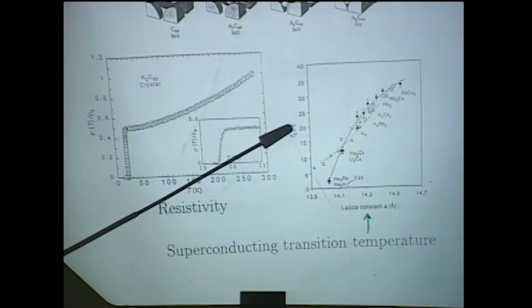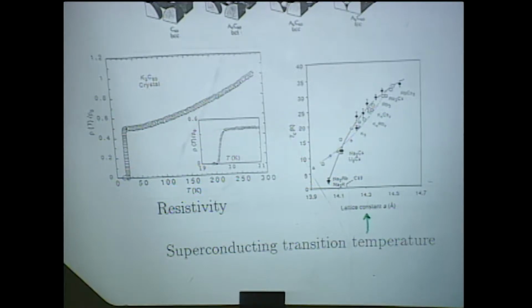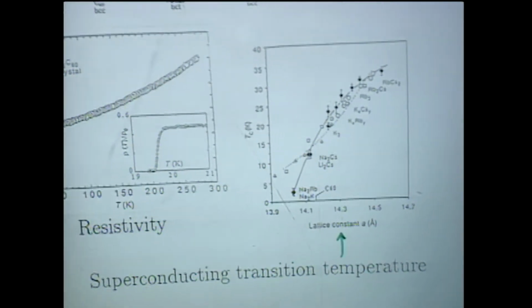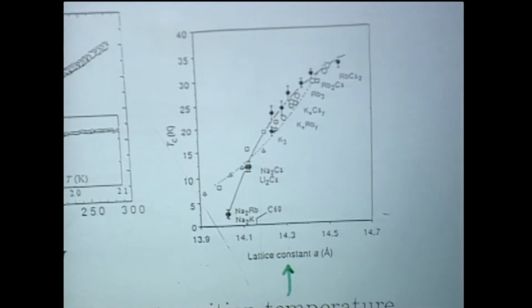This phenomenon was discovered in 1991. Unfortunately, it wasn't discovered in 1986. 1986 was when high TC was discovered, and buckyballs were discovered in 1985, and there was really no reason that high TC superconductivity in these materials couldn't have been discovered at that time, because the highest transition temperature until the year 1986 was 23 degrees. And you could see there are many doped buckyballs that have transition temperatures well in excess of that. The highest transition temperature in buckyballs so far is 40 degrees Kelvin.